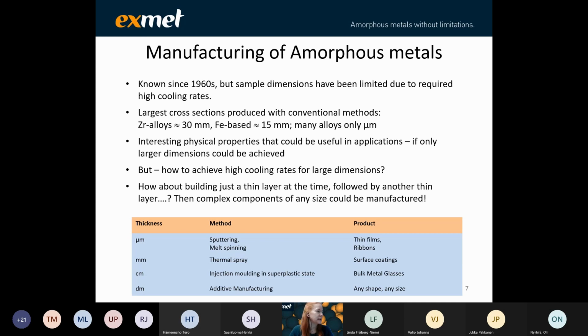Using these conventional techniques such as sputtering, thin films, and melt spinning, you end up with ribbons. You can use thermal spray to produce surface coatings. The largest cross sections that have been produced with these conventional methods are measured in micrometers or possibly millimeters. So even though these materials have interesting physical properties that can be useful in applications, the application has been limited due to these dimensional requirements.